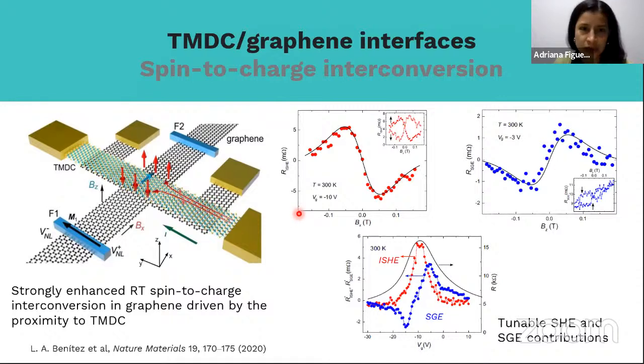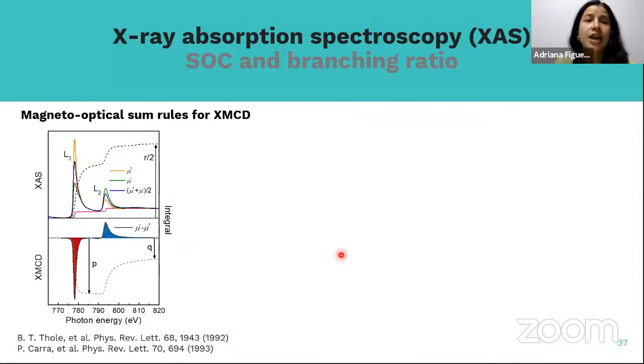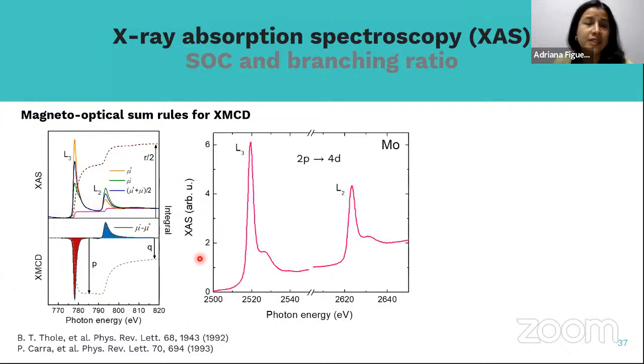But these kinds of measurements of proximity-induced spin-orbit coupling in graphene are not a direct measurement of the spin-orbit coupling induced in the graphene. So we wanted to explore other characterization techniques to study such spin-orbit coupling. For that, we are using X-ray absorption spectroscopy at synchrotron radiation facilities. Again, as I told you, it's the same technique that we use for XMCD, but in this case, we don't apply a magnetic field. We just study the X-ray absorption of the materials. For example, in this case, we study the X-ray absorption of the molybdenum in a molybdenum disulfide material interfaced with graphene.